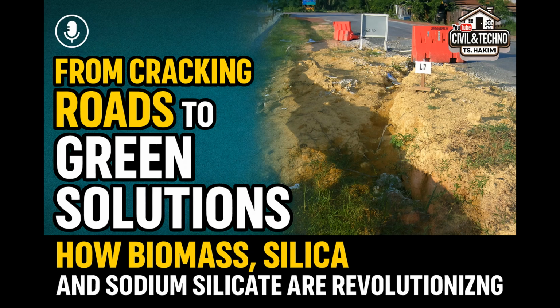Gives you confidence. Okay, so they did all these tests, macro and micro, short-term and long-term. What did they find? Did this SH85 and TX85 combo actually deliver for Batu Pahat soft clay? It really did. The results were quite striking, actually. First off, they pinpointed the best recipe, the optimal mix. The sweet spot. Yeah. It turned out to be 3% sodium silicate, that's the TX85, which they called 3L, combined with 9% biomass silica, the SH85, called 9P. 3L and 9P. Okay. Finding that optimal blend was a key result in itself.